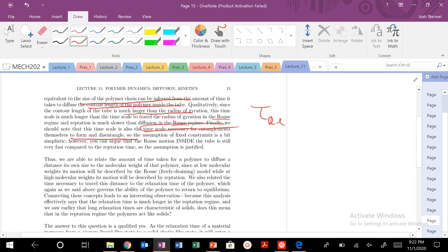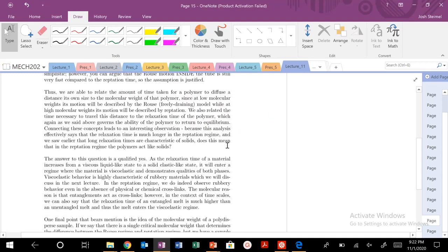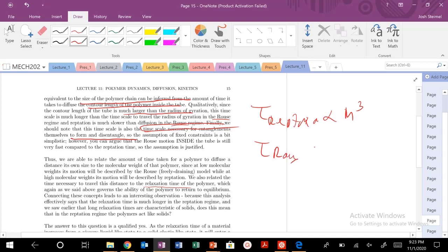That time is going to be much longer because it has to move the size of that tube, which is the contour length of your material — much larger than the radius of gyration in the Rouse regime. τ_reptation scales with M³ and τ_Rouse scales as M². A very, very big difference. The key idea: in reptation you have topological obstacle constraints, while in Rouse your polymer is moving through a viscous fluid relatively unconstrained.